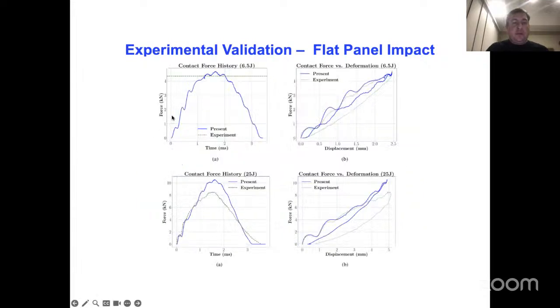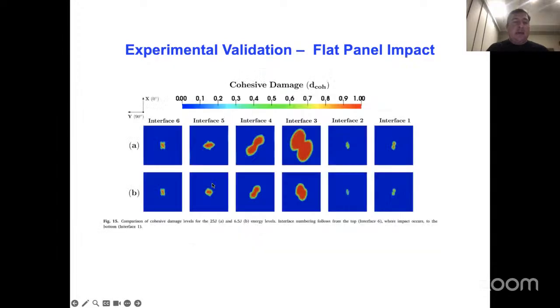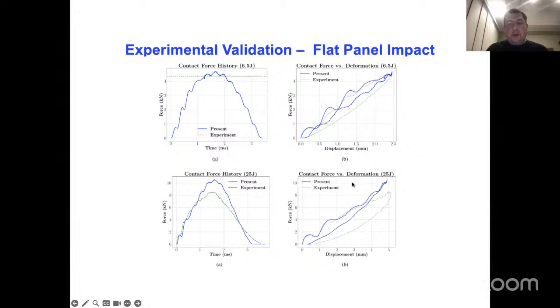Here's a contact force history for the 6.5 joule case. Only the peak forces are given. We're matching those pretty well. For the 25 joule case, the duration of the impact is predicted very well, but there's some discrepancy in the peak force, probably having to do a lot with, again, boundary conditions and the inability to generate enough delamination in the rear interfaces.